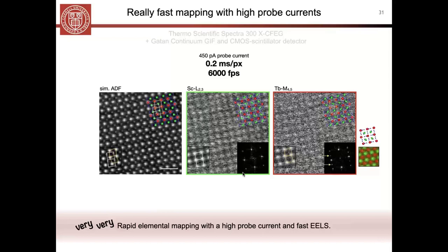And so being able to tie back these kinds of reciprocal space lattice symmetry information back to the local chemical information that we can extract from EELS, uniting those two things in a single measurement, is going to be very, very powerful for us.